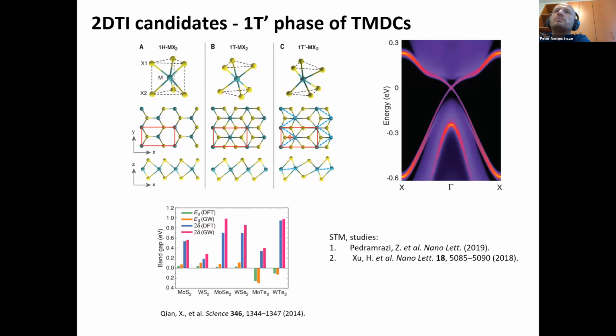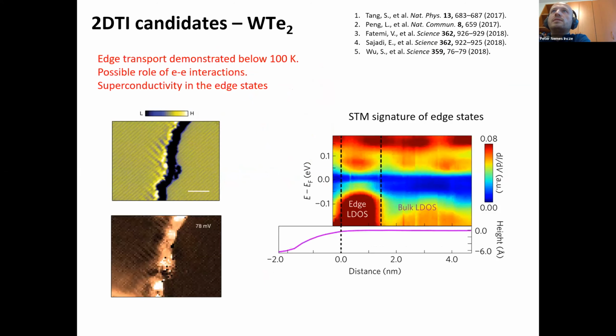And there's been a very good theory paper in Science, which actually showed that all of them are quantum spin Hall systems if they are in this 1T prime state, which I mentioned is a metastable state for most of them, with the exception of tungsten telluride. And indeed, in the case of tungsten telluride, it has been shown by STM and also transport measurements that it is almost for sure a topological insulator with protected edge states. And it has a host of other interesting properties, which I will not go into at the moment.